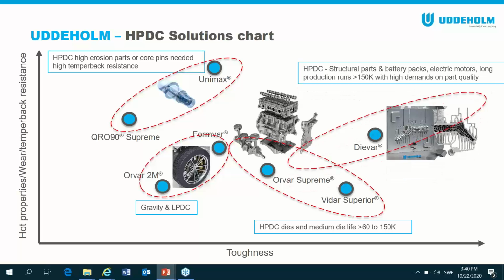And then finally we come to Dievar. So Dievar is the do anything material in effect. So for instance, it can be for dies for 60,000 shots and higher if it's structural, because they're a much lower die load. It can also be for long running tools if they're medium size. I showed you the example of the one that did 150,000 shots in the heat sink and went on to do 250,000 with the coating on it. So that's where our materials would sit.